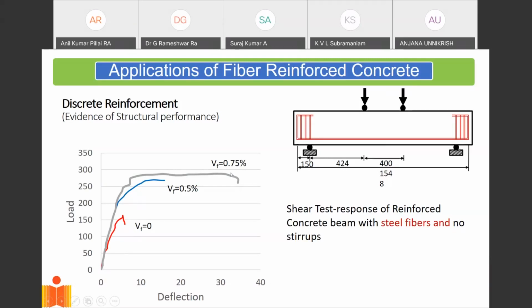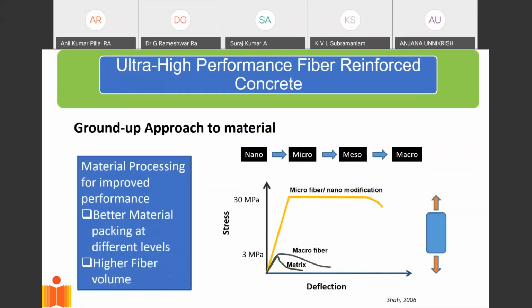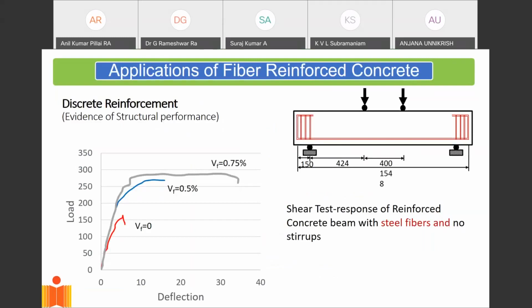So at about 0.75% volume fraction of the fibers, so 0.75% of the total volume of concrete is in the form of these steel fibers, we are able to achieve a tremendous improvement in the shear capacity and also produce a nearly ductile response, where the load remains constant for a very large amount of deformation. So this is mainstreaming of application of fibers in structural applications. This is as far as conventionally mixing fibers as alternate forms of reinforcement in concrete, which would allow us to reduce the requirement of conventional reinforcement bars in concrete.